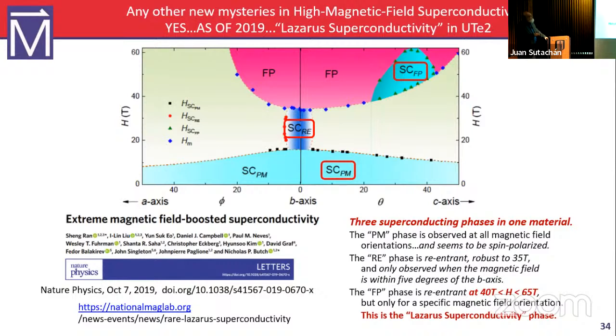Nobody has a clue what's the physics behind a superconducting phase that is so robust, it occurs at magnetic fields that should destroy the superconductivity for a superconductor that has to be 1 Kelvin to superconduct. Normally, if it superconducts below 1 Kelvin, less than 1 Tesla will kill the superconductivity. This superconducts at around 1 Kelvin, and yet it becomes a new superconductor at 40 to 60 Tesla.